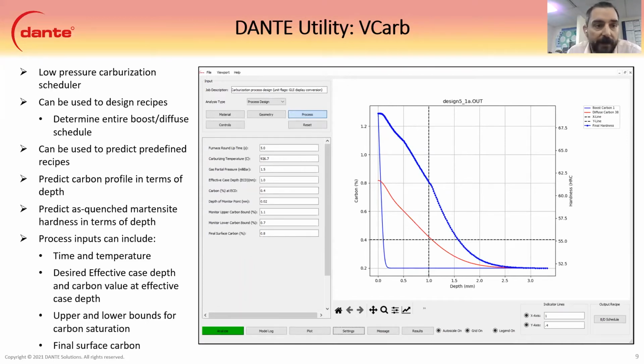It also gives you a hardness of as quenched Martensite. Like we said, we didn't have the other diffusive phases in the mixture law there, so we put in the as quenched hardness so we can know what you would get out of it if it was 100% Martensite. And then the process inputs here, we have material, geometry, and process is the main thing here, and then some controls. You're looking at the process screen right now, and this will let you know what we can input in here. So we have some furnace ramp-up time, so how long it takes to get to the pressure level you're looking for, or carbon level you're looking for.